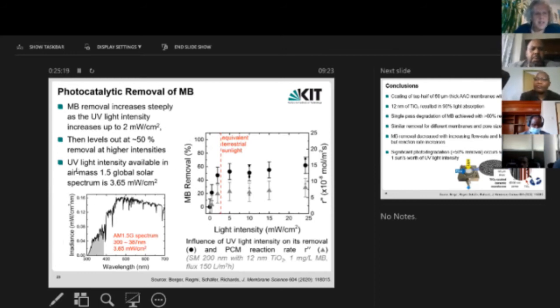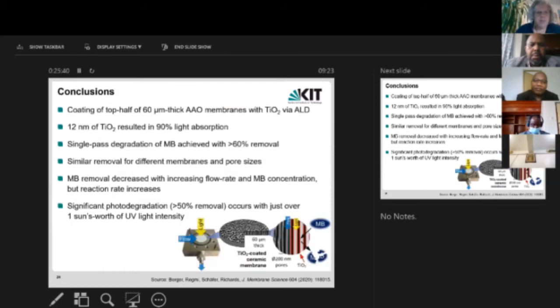Now I'd like to highlight that this amount of light, 2 milliwatts per centimeter squared, is roughly half what is available in terrestrial sunlight. The terrestrial sunlight, if we look at the AM global spectrum, has about 3.65 milliwatts per centimeter squared, as shown in the bottom left-hand graph. So with roughly half a sun, we're able to achieve good degradation.